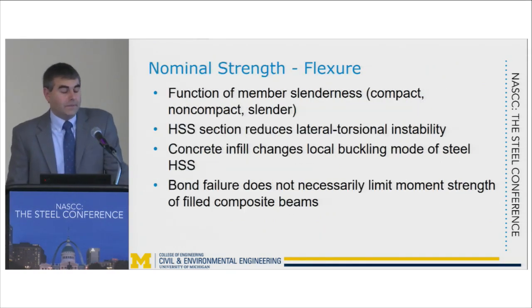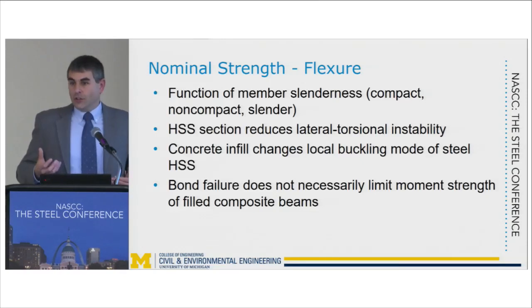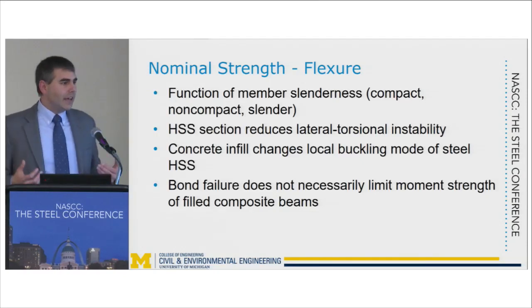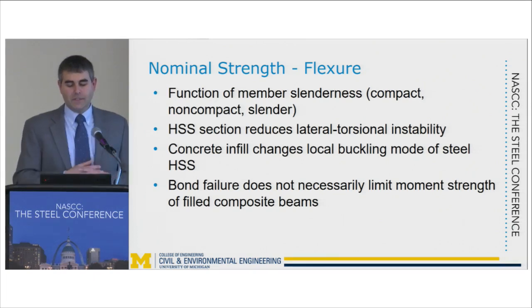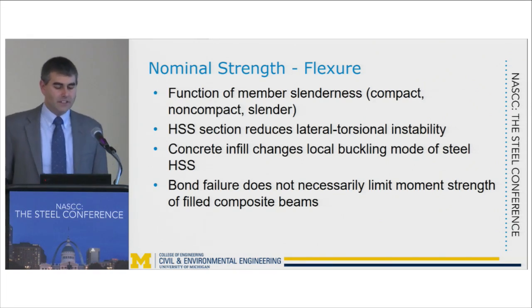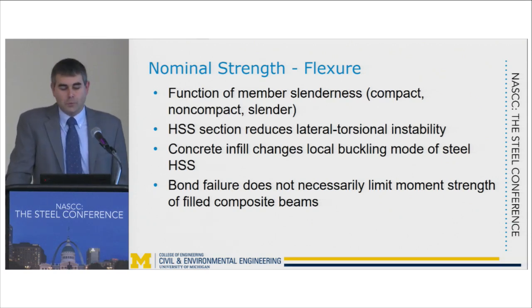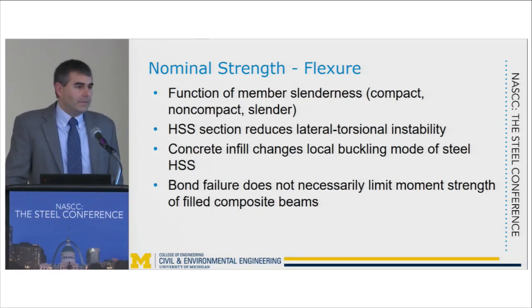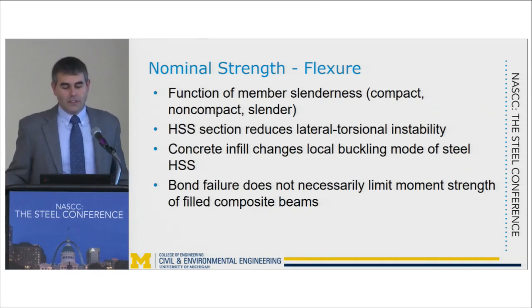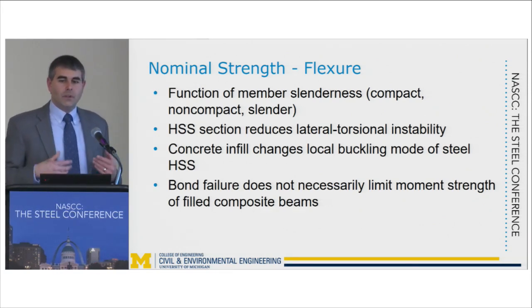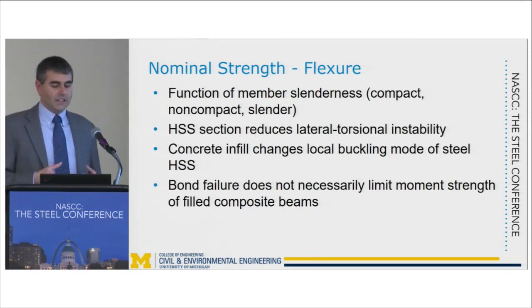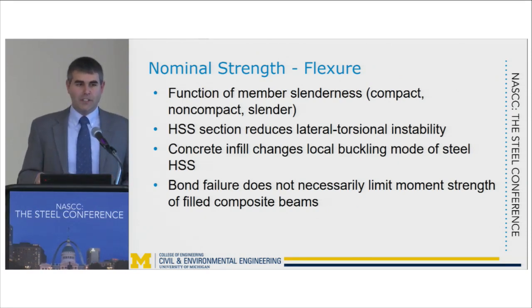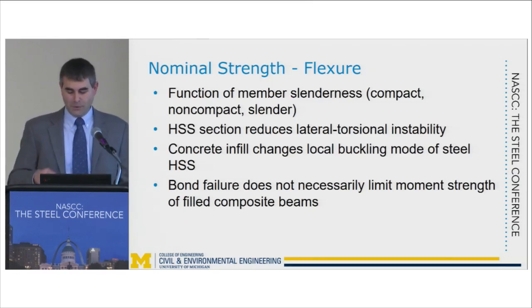Now we can consider nominal strength in flexure. Again, this is going to be a function of the member slenderness, whether it's compact, non-compact, or slender. Now, the HSS section alone has good torsional rigidity, but then you add the concrete to it and you get further reduction in the potential for lateral torsional instability, which is a benefit in terms of lateral bracing requirements. The concrete infill, as we mentioned before, does change the local buckling modes of the steel. But as I mentioned also, the bond failure between the concrete and steel does not limit your moment strength here. So it's not really a disadvantage when you're looking at a concrete-filled hollow structural section in flexure.